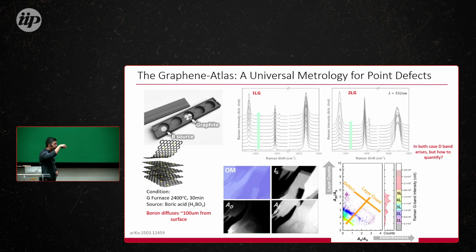However, we cannot do that when you have few-layer graphene systems. Because when you're measuring the Raman spectra, for instance, the scattered light will have different signals, right? Because of the thickness, one layer will maybe be more enhanced than the lower one, basically. So the intensity is not a good metric for that. So we propose something very different, and it is quite simple.